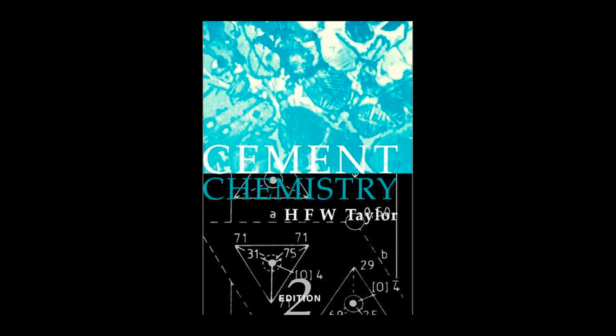So the production method has to be adjusted. The manufacturer increases the ratio of alumina, Al2O3, to iron oxide in the raw meal. But the real secret is in the firing and cooling. Okay, what do they do? They have to produce the clinker under slightly reducing conditions, so less available oxygen, and then, this is critical, employ extremely rapid quenching the moment it exits the kiln.